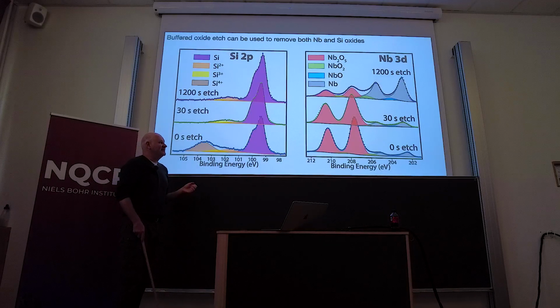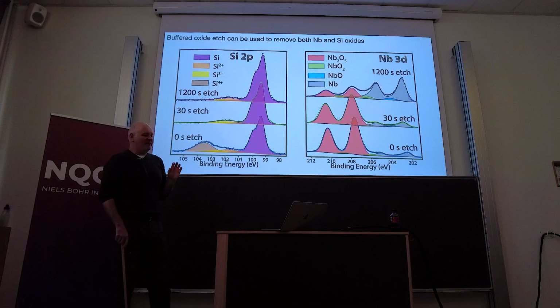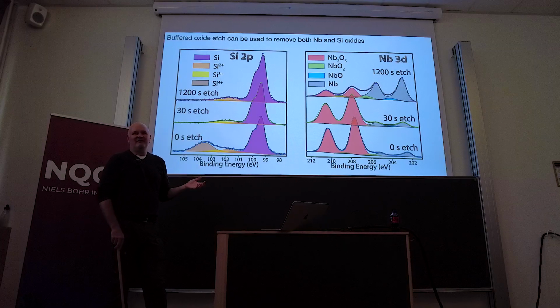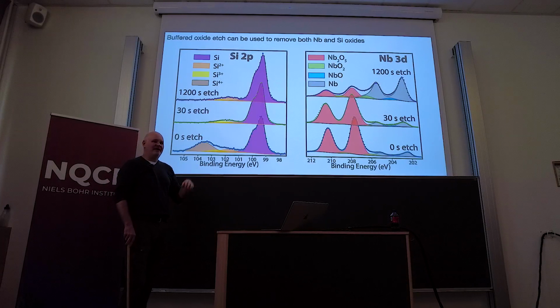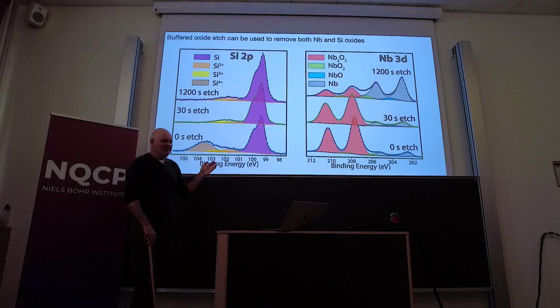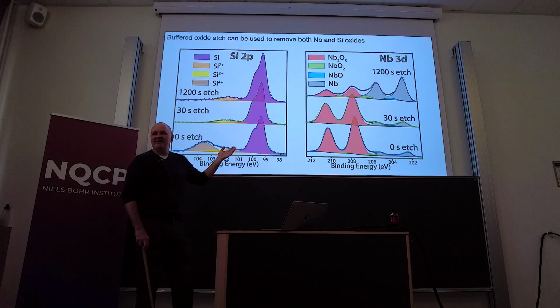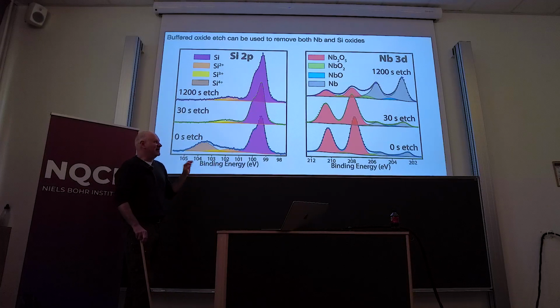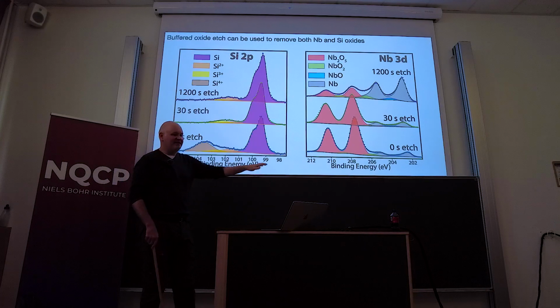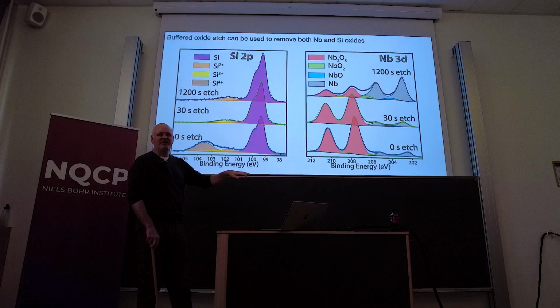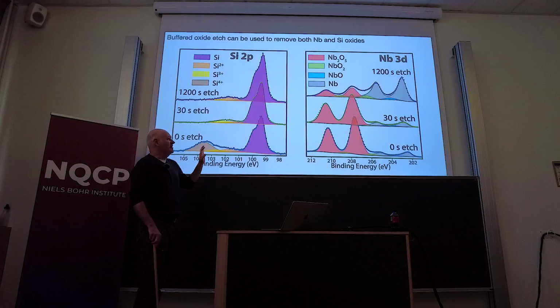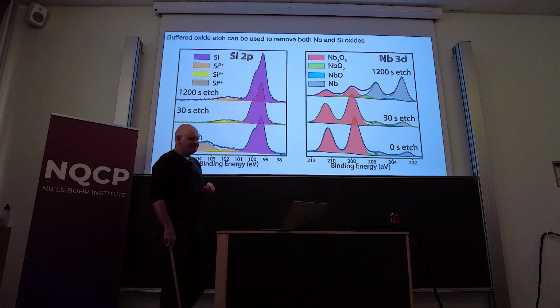It turns out that with pure buffered oxide etch, it's almost impossible to remove all of the oxide, most likely because by the time you've gotten it out and cleaned it off and rinsed it and loaded it into the XPS, it's reoxidized to some extent. It doesn't have a protective layer the way that silicon does. Silicon has these protons that basically line the surface when you do HF dips. It appears that niobium doesn't really ever get that.